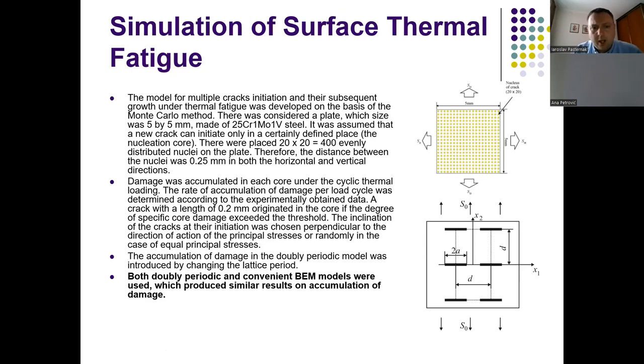That was a parameter for another model. The Monte Carlo method used in the first model was also used in the second to define the cracks density, to define the dependence of the distance between cracks on the number of thermal fatigue cycles. Also the loading was applied as sigma zero, which was the same as in the previous model, defining the thermal fatigue loading on the specimen.